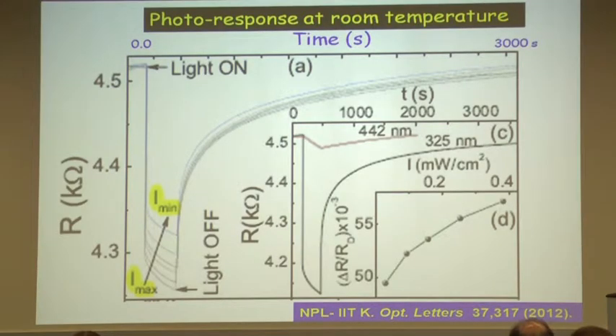So now, how do we do that experiment? Initially, my sample sheet resistance is close to about 4.5, 4.6 kilo-ohm. At this point, we open the shutter and expose the sample to the quartz halogen lamp light. And you see this dramatic drop in resistance. And it continues to drop. And at this point, if I switch off the light, it starts recovering. But it takes forever to recover. Look at the time scale here, about 3,000 seconds.